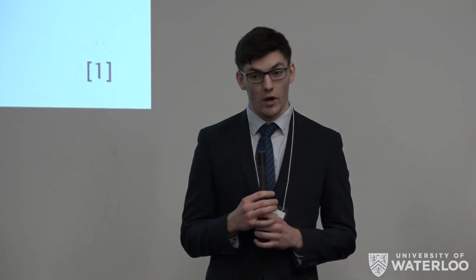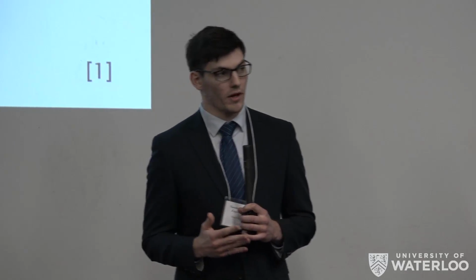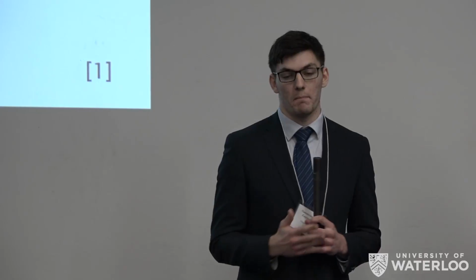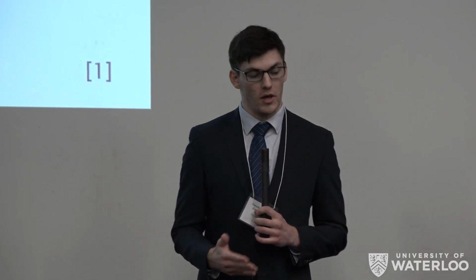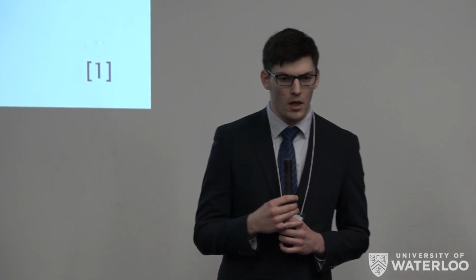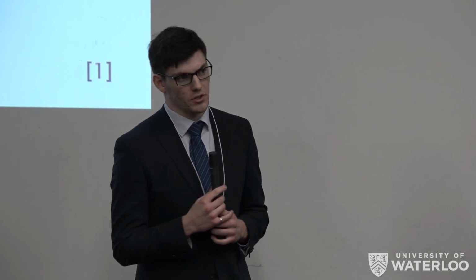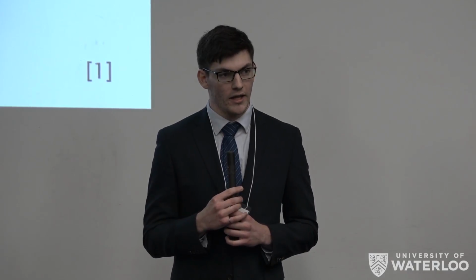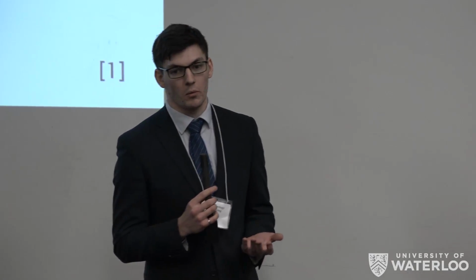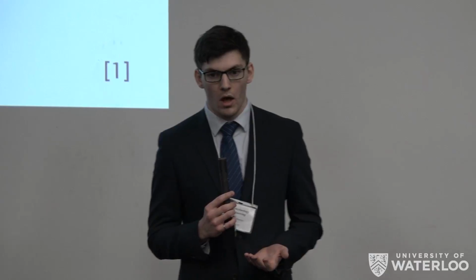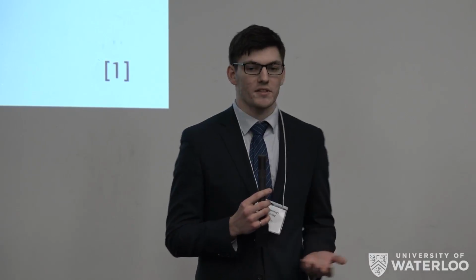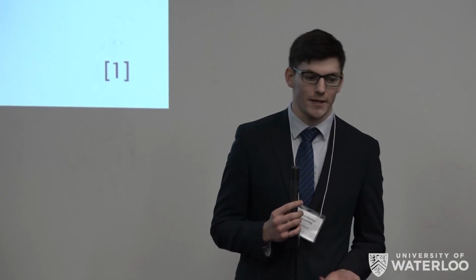So what's great about this method is since you've sort of got this weak interaction, you can actually get millisecond response times. So that would be perfect for building these high resolution maps that we want to build. The main problem with this method is that as we're using intrinsic graphene, it doesn't have any specificity to it. So it will interact with any polar molecule, and so you'll know that you have a signal, but you don't actually know what you are detecting.